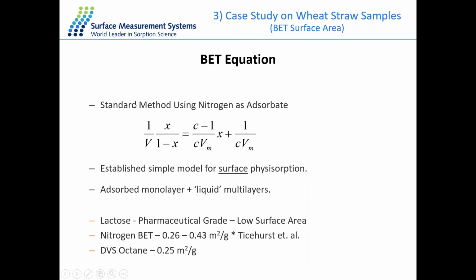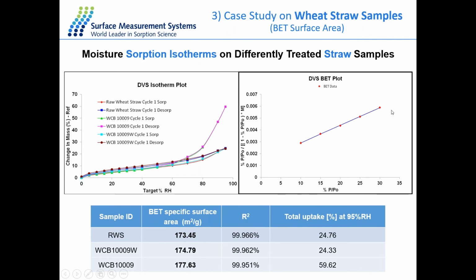And because the shape of this isotherm is very similar to a type 2 isotherm, we can also apply the BET equation, the same as the volumetric technique, to calculate the monolayer volume as well as the sorption constant from the sorption isotherm. And then with the cross-sectional area of the probe molecule, we can get the BET line for the samples and then calculate the BET surface area of the material. So in this case, we get a really perfect linear BET plot for all the 3 samples.